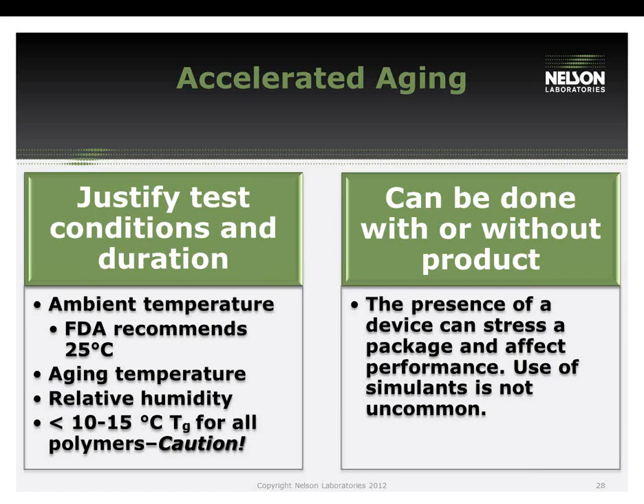Additionally, you want to make sure that you consider relative humidity. The standard indicates that humidity is not a factor for accelerated aging. So when you use your laboratories to do accelerated aging, make sure that humidity is controlled. Humidity has no effect as part of the accelerated aging. If you want to look at humidity effects on packages, you should do that as part of the transportation storage tests, along with climatic stressing and that type of stuff. So don't do it as part of the accelerated aging.